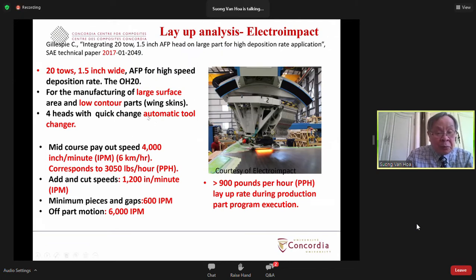So this slide here, again from Electroimpact in 2017, they give some of the speed and the position of the head. This one here is the head from Electroimpact. And in this case, it has 20 tows, 1.5 inch wide. So each time it can lay down 30 inch wide of the materials. And here they lay down on a large surface with low contours, with four heads. The maximum speed that can be laid down is 4,000 inches per minute, which is equivalent to 6 kilometers per hour. And that corresponds to more than 3,000 pounds per hour of material deposited.